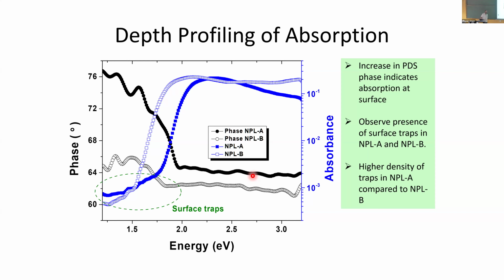So the depth profile basically depends on the sample being optically transparent. So the condition we place while doing this is that the absorption coefficient alpha multiplied by the thickness should be less than 1.